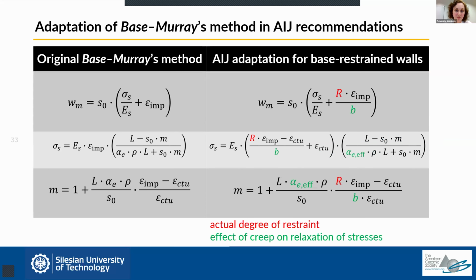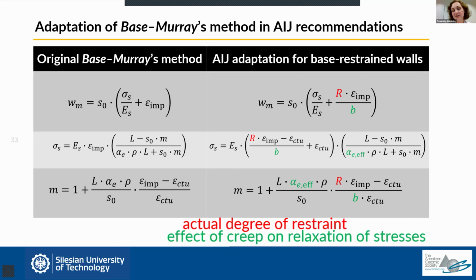Nevertheless, we can see in these equations some similarities to the European approach. So we can see that the stresses and the resultant crack width depend also on this restraint part of strain. On the left, you see the original method, which was developed for a fully fixed tie. And to the right, you can see an adaptation which was prepared for a partially restrained element such as walls. So the difference here lies in the fact that we take into account the actual degree of restraint, and also that we account for the effect of creep, which is of great importance at the hardening stage when the value of creep is really high.